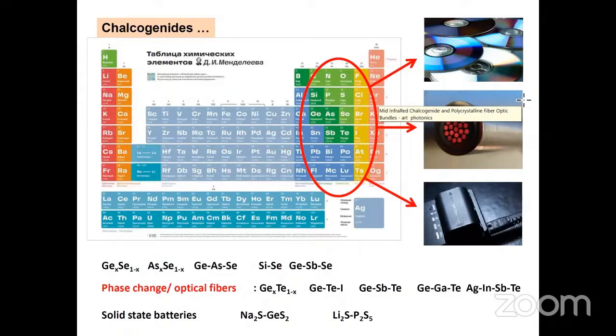The interest of all these glasses or amorphous systems is, in fact, that you can almost continuously tune the composition from, let's say, 0 for pure selenium or pure tellurium with various compositions to target a certain number of properties. For example, we have just heard about GST, germanium, antimony, tellurium, which is used in optical data storage. I should also mention that you could eventually imagine the sulfide analog of silicates, for example, sodium thiosilicate or even germanate, which is used in solid-state batteries, or at least they can serve as promising model systems to improve the ionic conductivity.